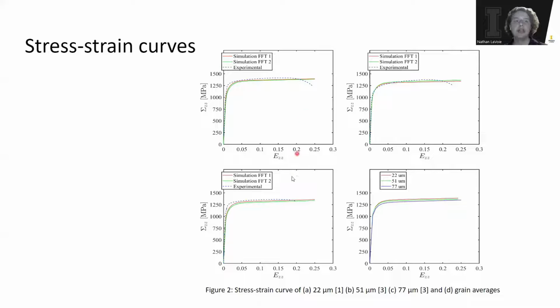In the 22 and the 77 average micrometer crystals, there was a high correlation in the elastic region, which can be seen here, a lower correlation at the yield point, which is here. You can see it starts to slip away from the experimental data. A moderate correlation at the strain hardening region, which can be seen here and here. Pretty close, but it can definitely get closer. And a low correlation at the necking and fracture point because we haven't taken into account that part of the mechanical properties yet.